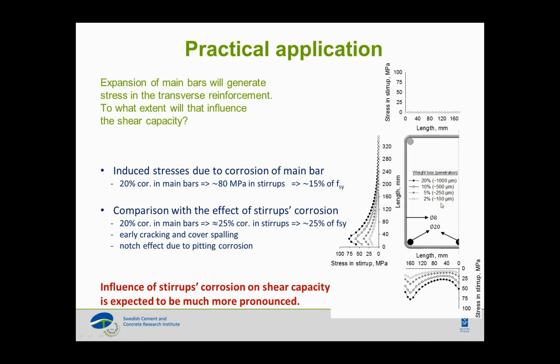So in this case, we try to look at a cross-section. This is half a cross-section. We have one reinforcement on the top, one reinforcement on the bottom in the corner, and one reinforcement at the middle of the section, and we have one stirrup all around it. So we try to impose corrosion on these two bars on the bottom, and then study the stresses in the stirrups. So down in this curve, what you see is the stress in the stirrups, and here is along the stirrups. So what you see is that here we have this main reinforcement corroding, and that imposes some stresses on the stirrups.